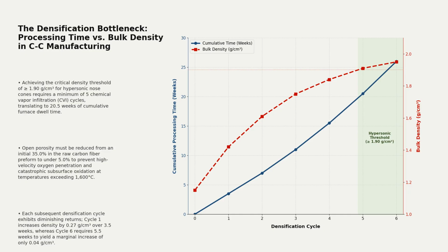The kinetics of densification exhibit steep diminishing returns. The first cycle adds 0.27 grams per cubic centimeter in 3.5 weeks. By contrast, the sixth cycle requires 5.5 weeks to add a marginal 0.04 grams. This kinetic bottleneck prevents rapid scaling through simple capital injection.